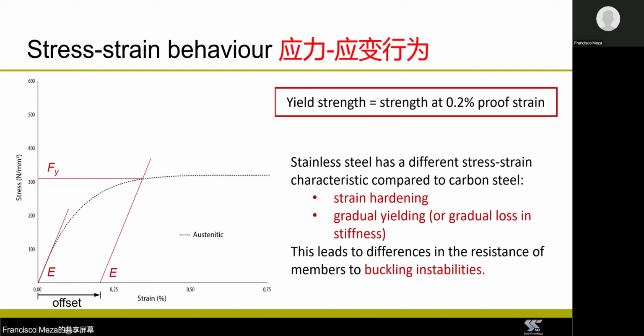Now, for stainless steel, the yield point is not well defined, and the stress strain curve shows this rounded shape without a sharp yield point. Because of this, the yield stress of stainless steel is obtained by offsetting the initial modulus of elasticity, which is represented by this red line, to a strain that is equal to 0.2%. Now, the point at which the red line intersects the stress strain curve is what is considered to be the yield strength.